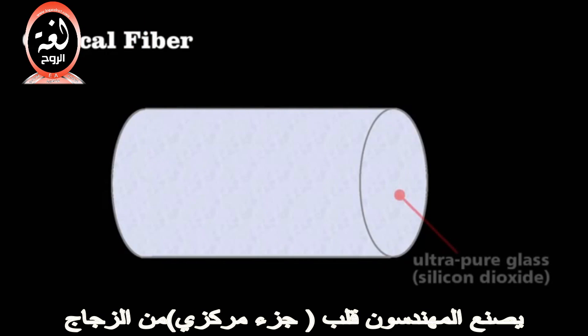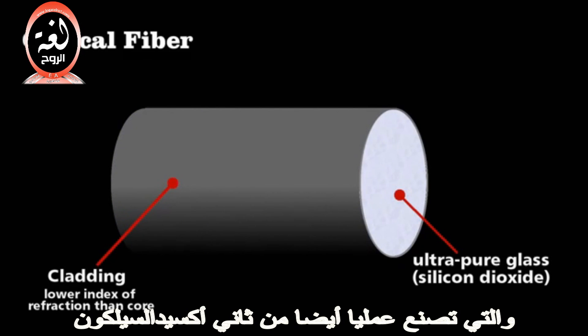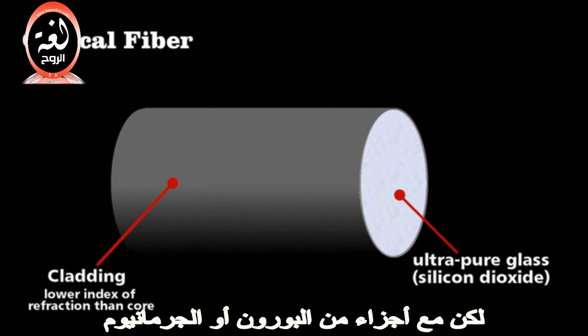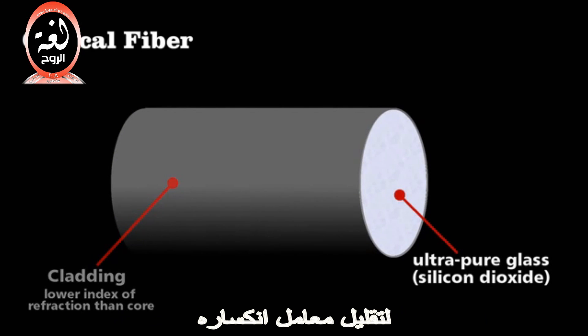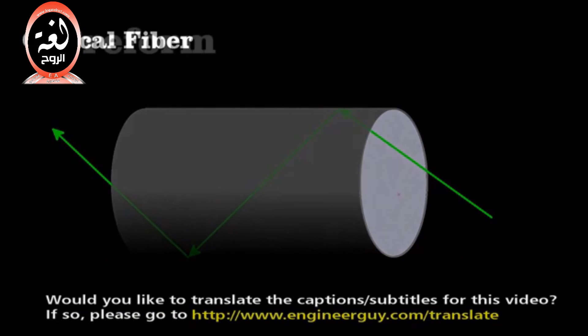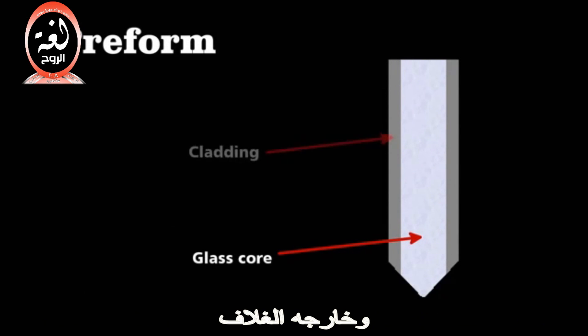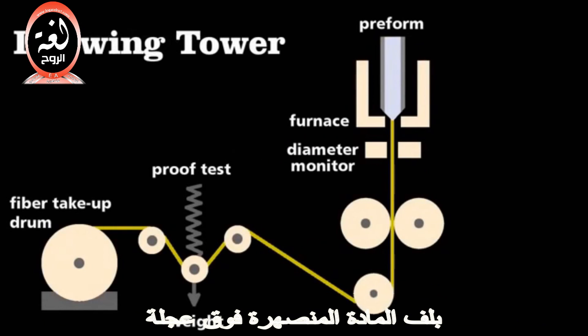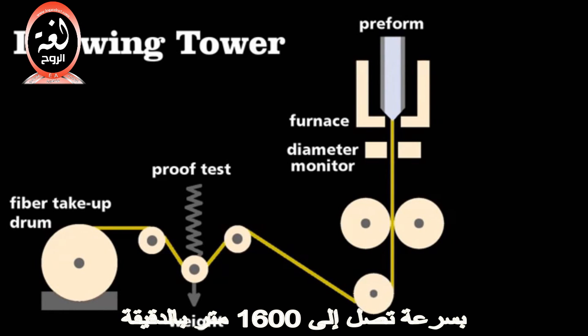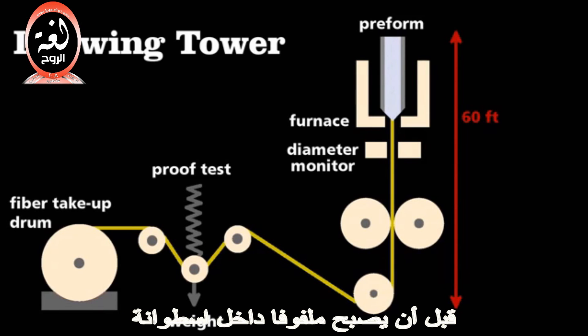To create this same effect in an optical fiber, engineers create a core of glass, usually pure silicon dioxide, and an outside layer called cladding, which they also typically make from silicon dioxide but with bits of boron or germanium to decrease its index of refraction. A 1% difference is enough to make a fiber work. To make such a long, thin piece of glass, engineers heat a large glass preform — its center is the pure core glass and the outside the cladding — then draw or pull a fiber by winding the melt onto a wheel at speeds up to 1,600 meters per minute. Typically these drawing towers are several stories tall; the height allows the fiber to cool before being wound onto a drum.